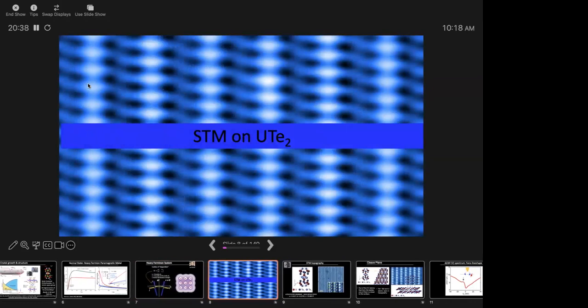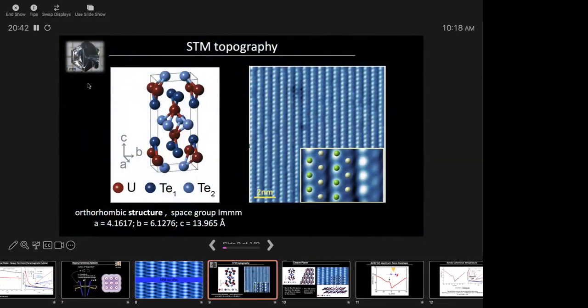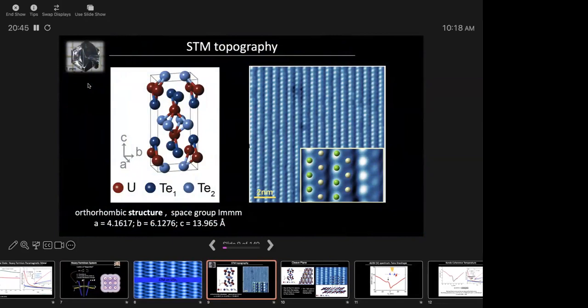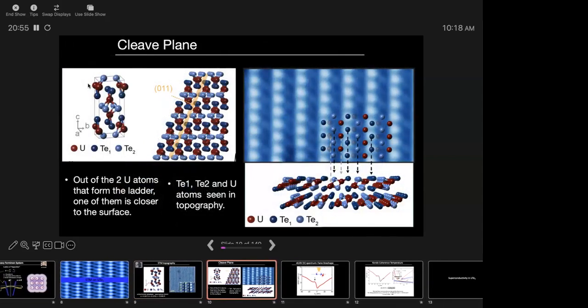So now let me show you STM data on UTe2. Here's topography, and here's the crystal structure. Looking at this, you don't realize that this might even cleave. Doesn't look like a material that wants to cleave, but in fact it does. It cleaves along this plane, which is the 011 plane. And we know that because we can look at the heights of the step edges, we can look at the distances between the atoms, and these are the tellurium atoms, right?